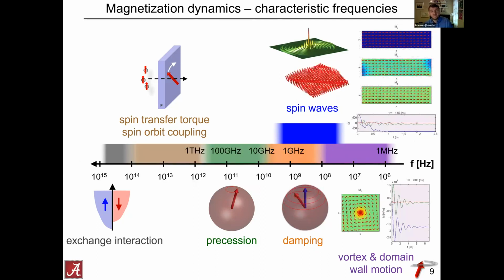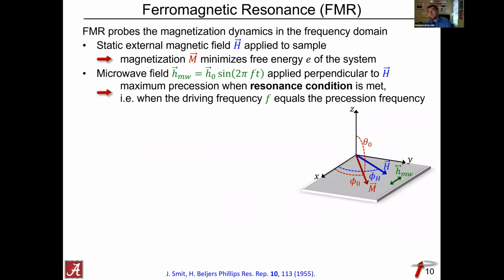So we're looking at things now in the frequency domain, which brings me to the technique that you can use to characterize these systems, which is ferromagnetic resonance. In ferromagnetic resonance, we probe the magnetization dynamics directly in the frequency domain. The way this works is you apply a static external magnetic field, and the magnetization will minimize the free energy of the system. On top of the static field, you also apply a microwave field that is typically applied perpendicular to the static field. You observe maximum precession when the resonance condition is met, that is, when the driving frequency equals the precession frequency.